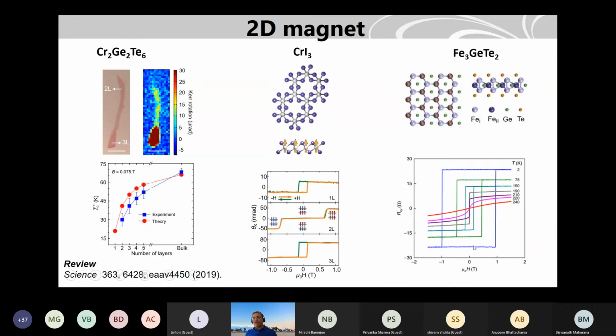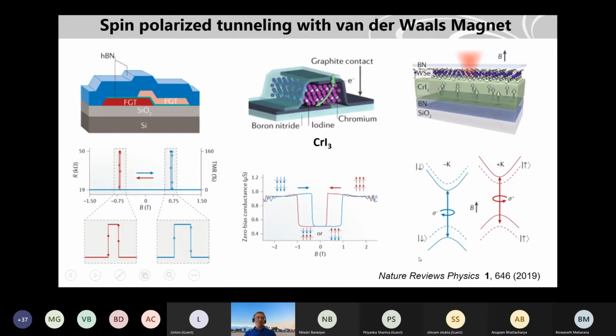You can directly measure the anomalous Hall effect. And there is lots of interest in these systems. Some of the devices you can make, like magnetic tunnel junctions with two FGT layers and a boron nitride tunnel barrier in between. Boron nitride is a good tunnel barrier, as I showed you. And one can see very high magnetoresistance, or tunnel magnetoresistance, in these structures.